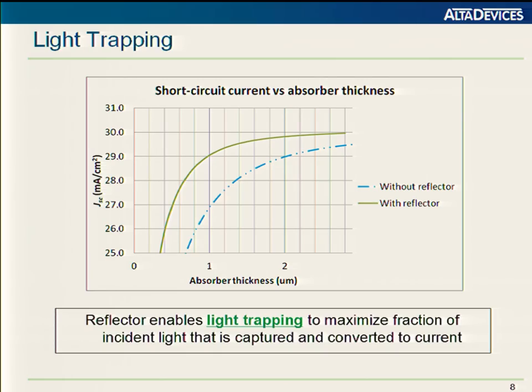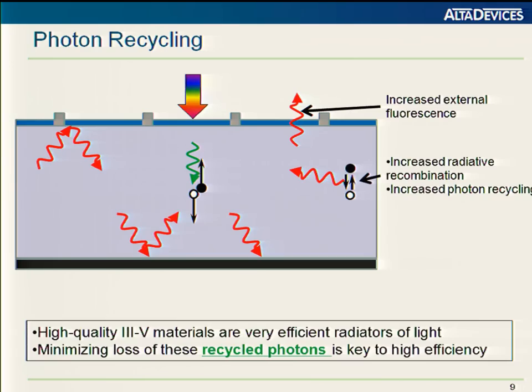So first, looking at short circuit current densities as a function of thickness. This can be significantly boosted for these relatively thin cells. And you can start to talk about achieving these industry standard JSCs with a device that's less than 3 microns. There's another phenomenon that's going on that's actually more important in terms of the performance boost you get from this geometry, and that is what happens with the band edge photons, the recycled photons.